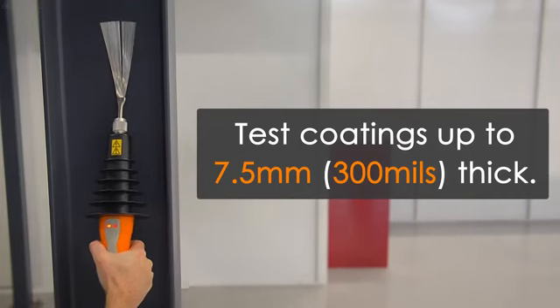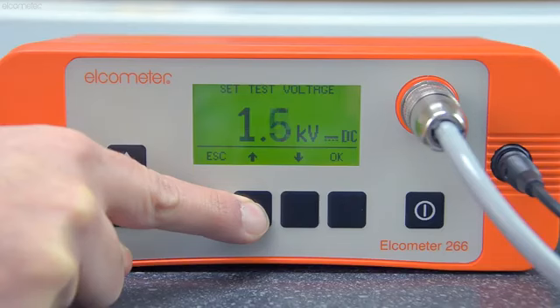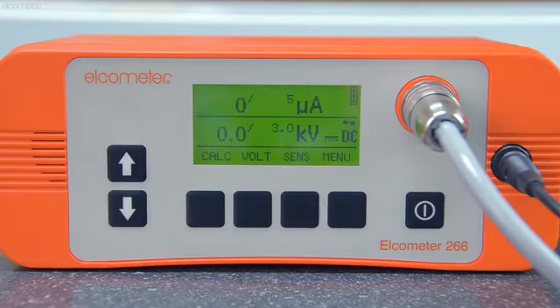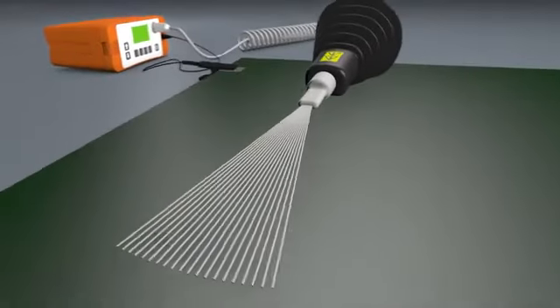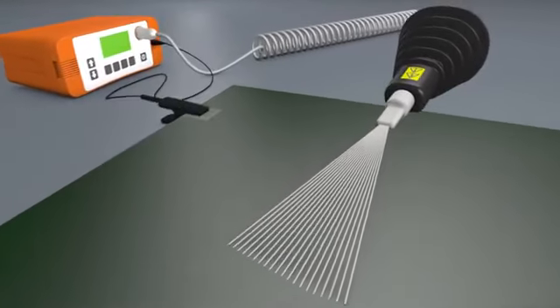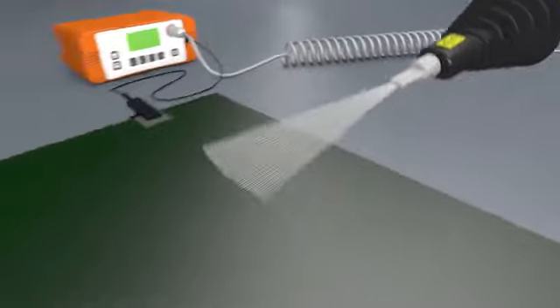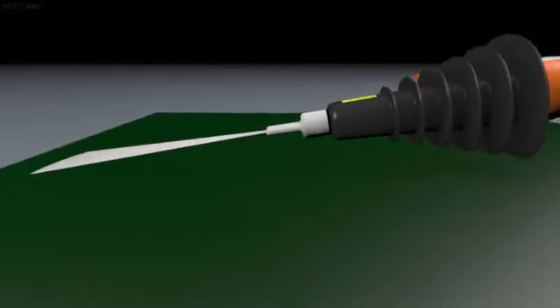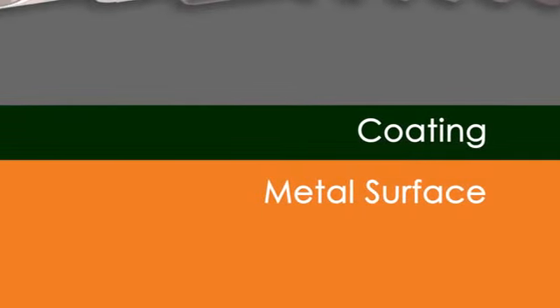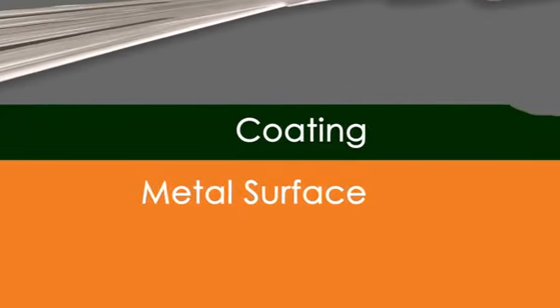So, how does it work? Put simply, a high voltage of between 0.5 and 30 kV is applied to a probe. The probe is then passed over the coated surface. The voltage to the probe is constant, hence the name continuous DC. The voltage used should be high enough so that in areas where the coating is electrically weaker due to a flaw or discontinuity, there is sufficient voltage to break down the gap between the probe and the substrate.